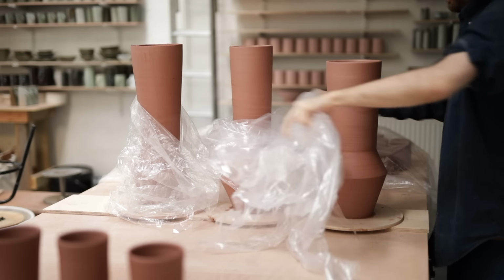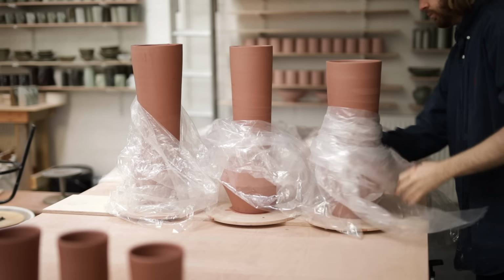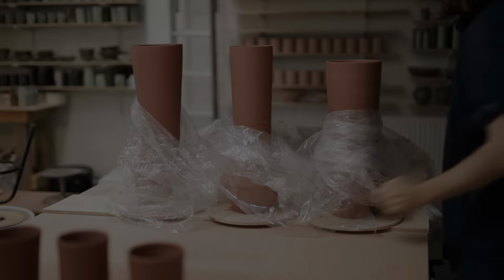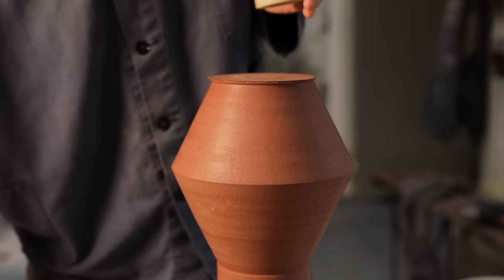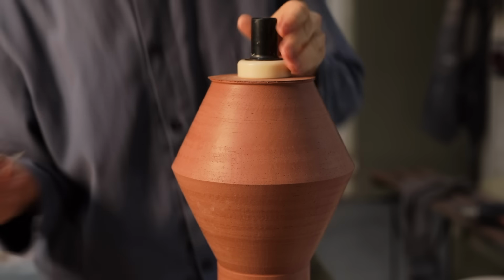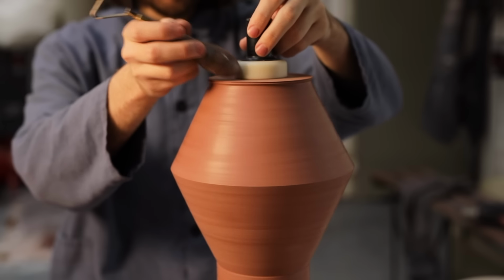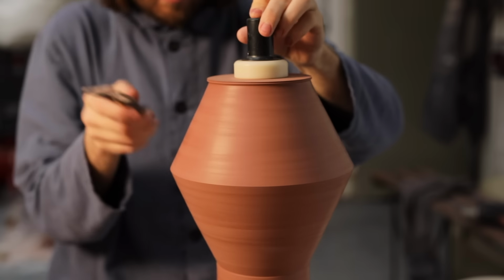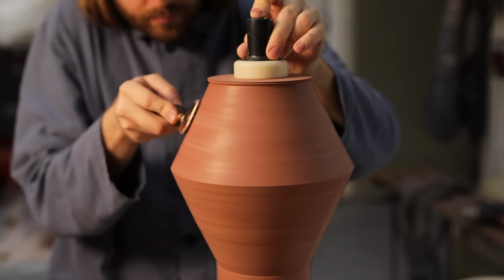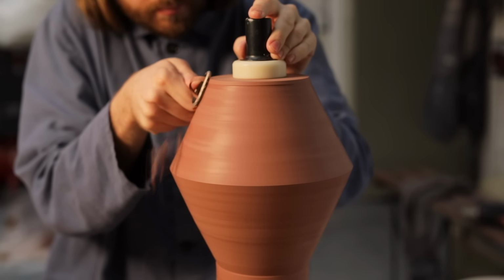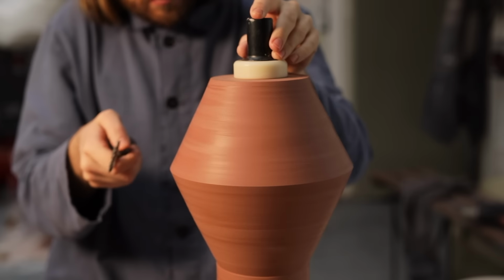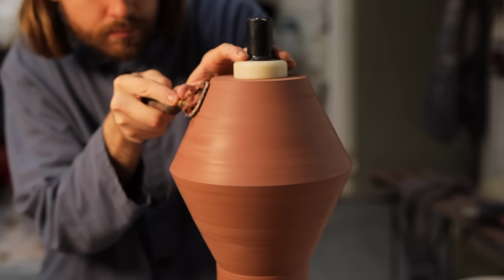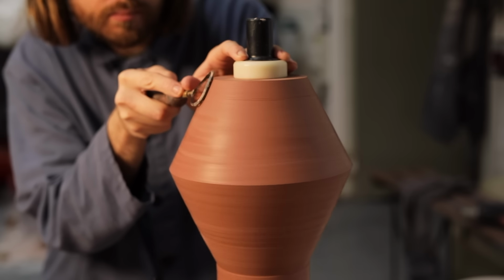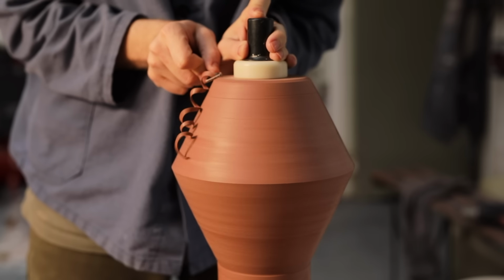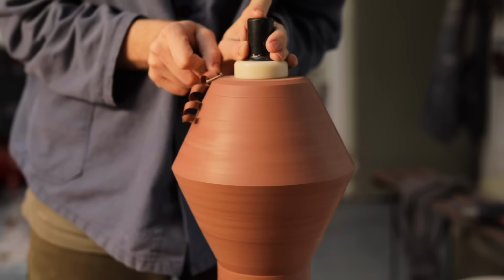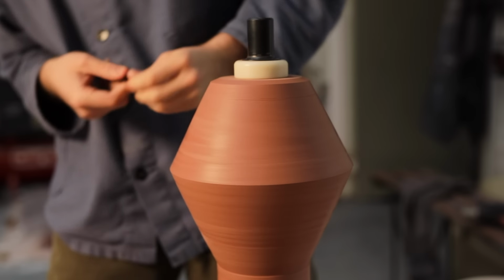The next step for these though is trimming, and in this case that was a difficult task as there were some quite serious wobbles I had to contend with. With that being said though, it's amazing what you can get away with, although ultimately what I thought I was getting away with is what led to some pots collapsing. And that was for this simple reason, as a few of these pots had an inherent wobble to them. It means I'd remove more clay from one side than the other, as I attempted to even out the overall form. This meant at the end that one side of the pot may have walls that are 2 to 3 millimeters thick, whereas the other side was closer to a centimeter thick.